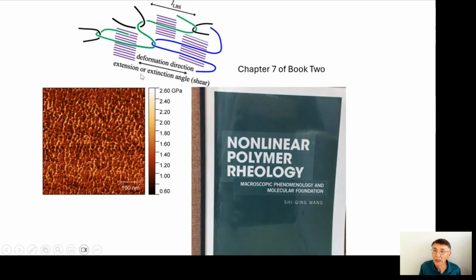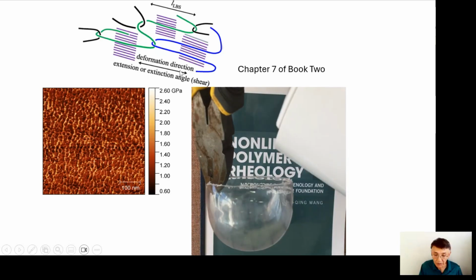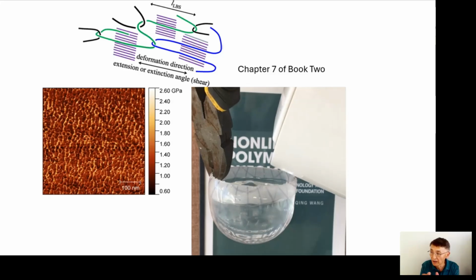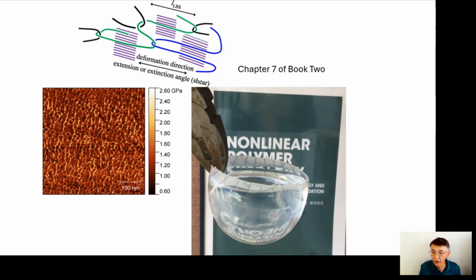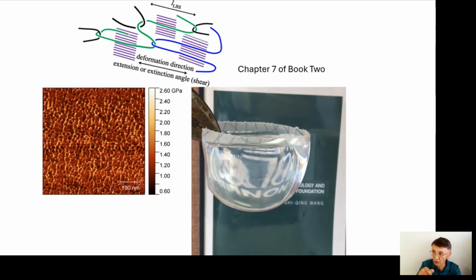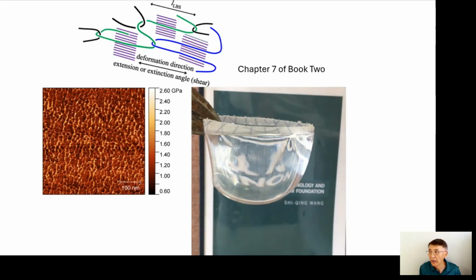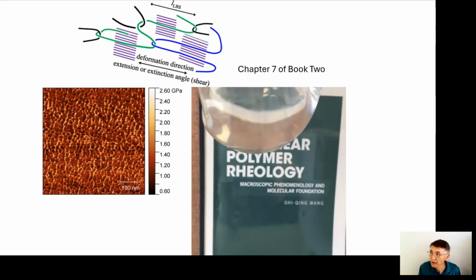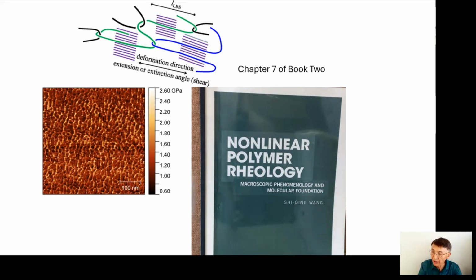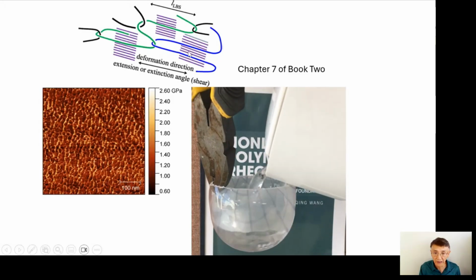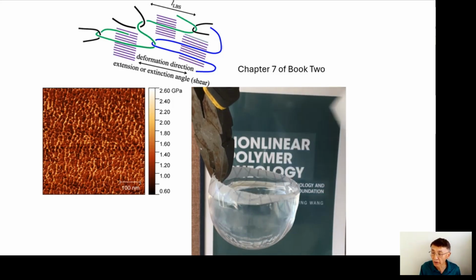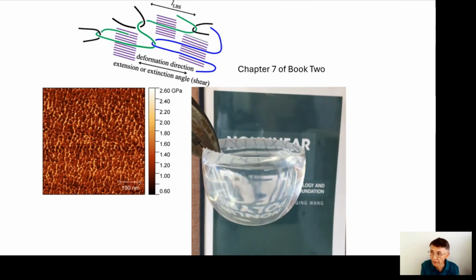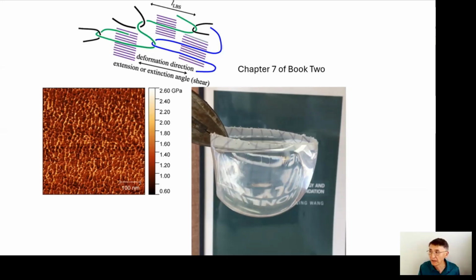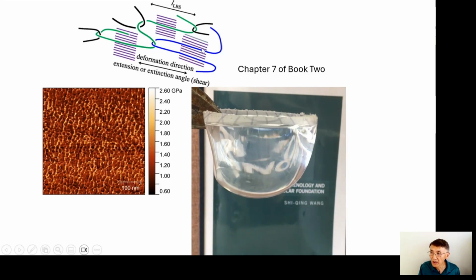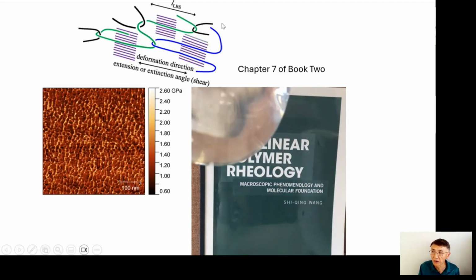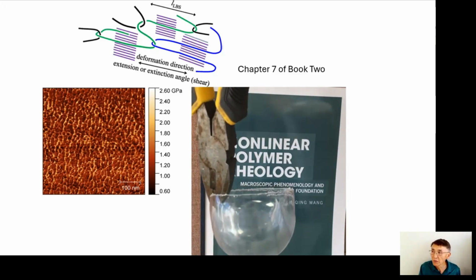But it's known to be brittle, but we know through processing, as we showed in the case of polystyrene, if you can melt process it, your polystyrene turns ductile because of this geometrical condensation. In fact, you can achieve that geometric condensation in both directions, to do so-called biaxial stretching. What was visualized at that time was that I realized that you can do this stretching in the melt state. And when the chains lined up, you also encourage crystallization. PET, PLA, they all can crystallize, but generally crystallize very slowly. But with enough local chain orientation, they can crystallize. And I envision that this crystallization will occur within each mesh size of the network. So the crystallization will necessarily be nanoscopic, and therefore making your product transparent. So this was the idea.